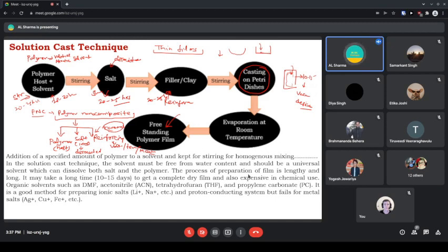And as it is a covered petri dish, you put it into the vacuum desiccator. Here extra silica gels are there, which absorb all the solvents present. And because there is vacuum, no other contaminants are going to get in. So you are going to get a very good film, a freestanding film, where the interactions of the substrate are nowhere involved, since once it dries it leaves the petri dish. Yes.